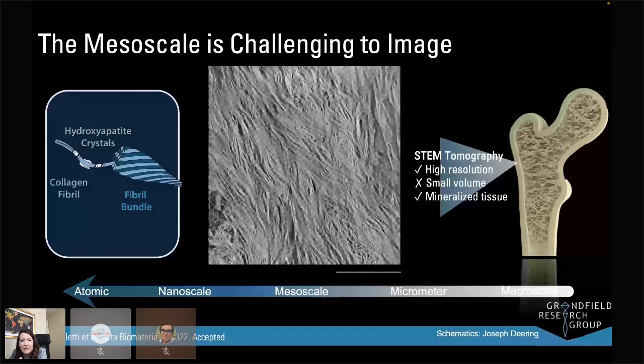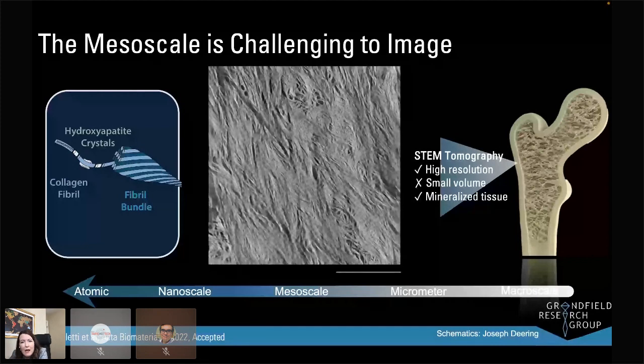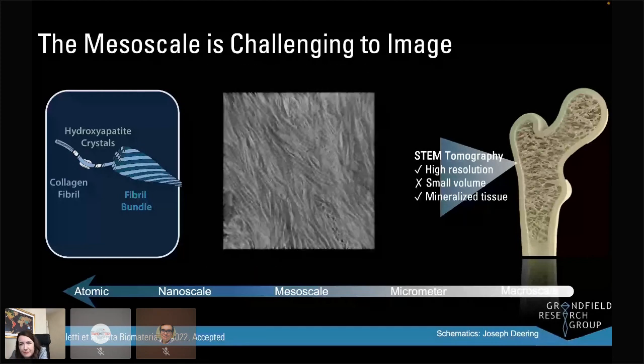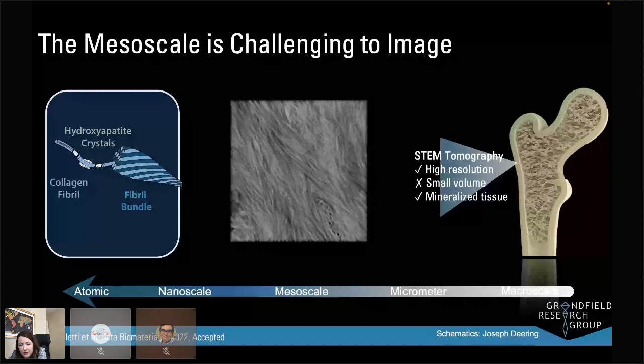Here's an example of a STEM data set from our lab of bone structure. What you can achieve is high resolution—you can look at mineralized tissue or demineralized tissue—but it has a major drawback in that it's a very small volume, less than 100 nanometers in thickness, maybe 200 nanometers. So we're missing a lot of the structure, and we're only looking at a very small region—a needle in a haystack, you could say.